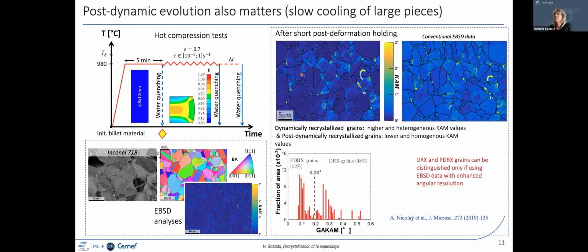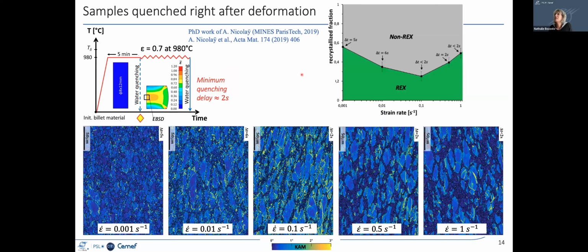All right, so here, these are, again, Inconel 718 samples, which have been submitted to such a hot deformation test. And those ones have been quenched immediately at the end of deformation. Here, immediately means experimentally as fast as possible. And on our machine, the minimum quenching delay is about 2 seconds. You have here on each of these maps the actual quenching delay or quenching time that could be achieved.